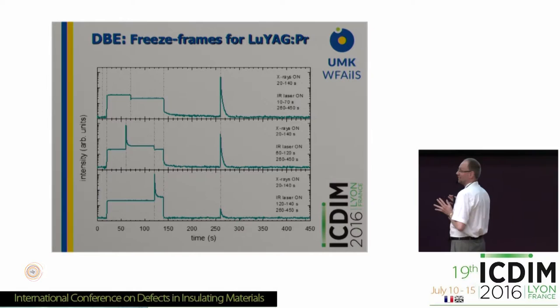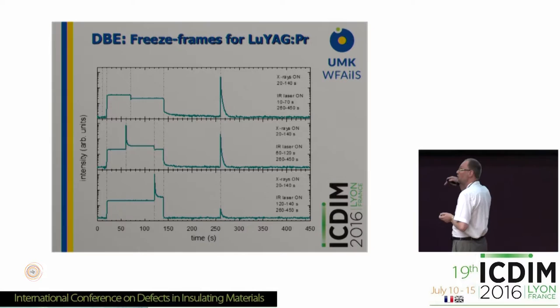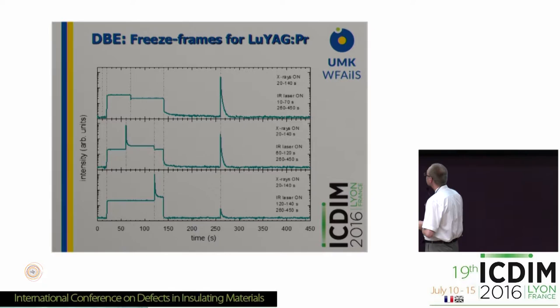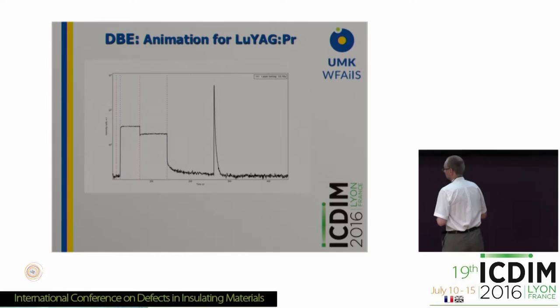We studied this in an automated sequence. When we irradiate the sample only with X-rays, we see the level of sample radioluminescence. If we impose infrared on the X-ray irradiation, the signal goes up — it is increased. Moreover, if the X-rays are on and we start infrared irradiation by switching on the laser, we see a kind of decay. And in one part, the X-rays are off but we switch on the laser and also see optically stimulated decay.